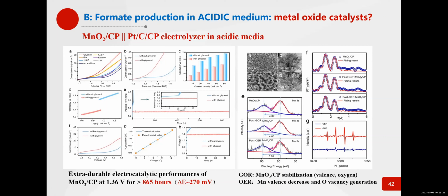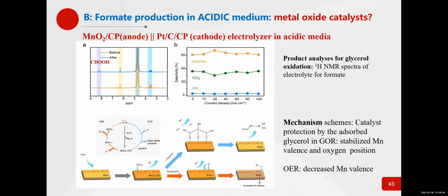Why is this kind of metal oxide, which is usually soluble in acidic media, so stable in the presence of some kinds of organic molecules? We have probed these materials in the production of formate in coupling with Pt/C at the cathode, and it shows good performance, and the Faraday efficiency for the formate is about 60%, and also there are some other kinds of products. And then we probe the mechanism why the material is stable, because it is protected by the added glycerol in the electrolyte.